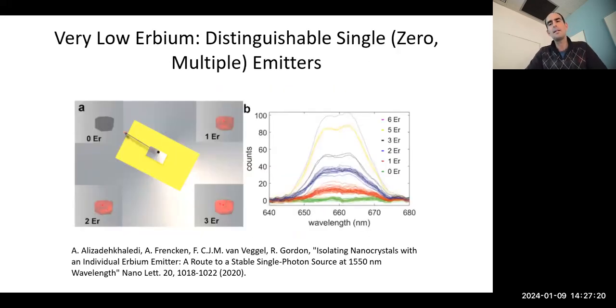So what do we do then? We asked Frank's group, Adrian Franken and others, to grow us nanocrystals that only contained, on average, 1 or 2 erbium emitters per nanocrystal. And then we repeatedly trapped these nanocrystals and measured the amounts of emission that we saw.